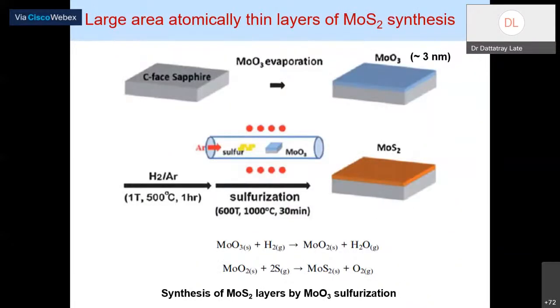So this is another very similar method. We have here MoO3 already coated on your SiO2 substrate. I have sulfur gas, with argon again as a carrier gas. What happens? When you pass hydrogen gas, you will be able to convert this MoO3 into MoO2 and H2O. This H2O goes out in the form of gas. And again, there is conversion of MoO2 into MoS2 with sulfur. Reaction happens between these two, and then you have MoS2 coated on these layers, and oxygen evaporates in gas form. So this is a simple synthesis of conversion of MoO3 into MoS2.